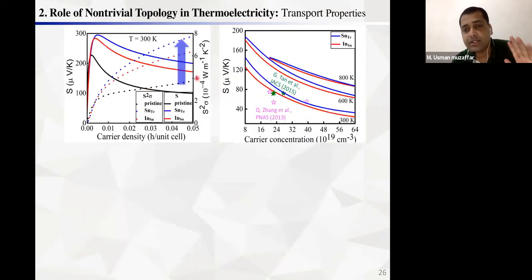So to directly confirm this conjecture, we calculated using Boltzmann transport theory, and you can see that along this direction, this is the Seebeck coefficient, and this is the power factor. The solid line represents the Seebeck coefficient, and the dotted line represents the power factor. Compared to the undoped case and the well-studied indium doped SnTe system, our predicted system has a much higher power factor. The well-studied system is published in a PNAS paper. So these are the transport properties at 300 Kelvin. Then we studied the Seebeck coefficient at high temperatures, and compared this data with the indium doped SnTe system. And in all these three systems, the anti-site doped system has a higher Seebeck coefficient.